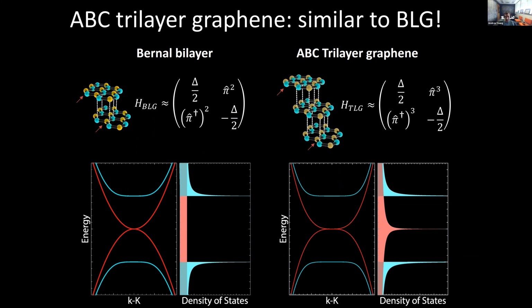That's very high energy, so that doesn't really happen physically. But then you have a choice of whether you're going to put the second layer in one of two ways, where one of the two atoms in the unit cell will be on top of another atom in the first layer, and the other will be in the center of a hexagon, and you have two different ways you can do that. So in Bernal, the stacking order is A, B, A, B, so it goes back and forth between two choices and doesn't realize the third choice. But in ABC, it means you actually are going to realize the third choice every third layer.